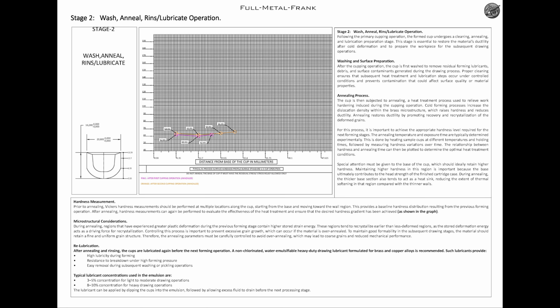Relubrication. After annealing and rinsing, the cups are lubricated again before the next forming operation. A non-chlorinated, water-emulsifiable heavy-duty drawing lubricant formulated for brass and copper alloys is recommended. Such lubricants provide high lubricity during forming, resistance to breakdown under high forming pressure, and easy removal during subsequent washing or